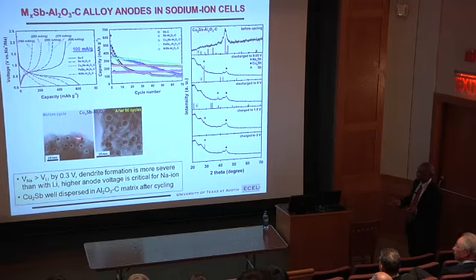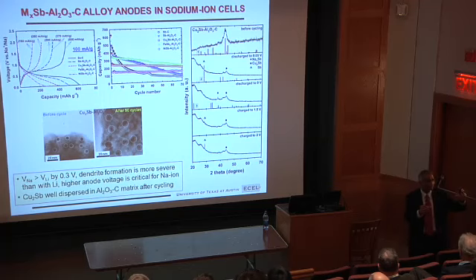And another thing you find is during cycling, the usual problem is these particles will come close to each other, grow, and become bigger. When they become bigger, volume expansion will be magnified, so the electrode will crack and they will fail. Here, as you see, it doesn't change too much.